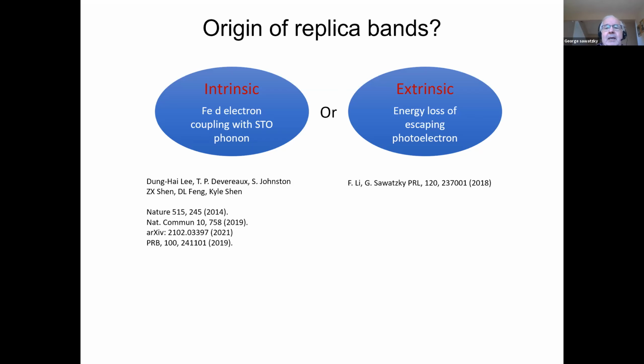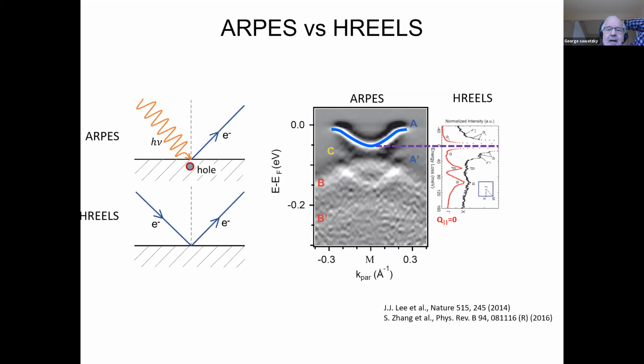Okay, very important. But it could also be that the electron on its way out is actually exciting phonons. This is very common in photoemission results, where you can have plasmon satellites, for example, coming in as shake-off peaks, people call them, and they could be extrinsic or intrinsic, caused by either the fact that you have removed an electron from the iron and have a hole propagating there, or for the fact that the electron going out is actually exciting the phonons. And those are on the left-hand side here, that shows these two different types of things that could be happening.